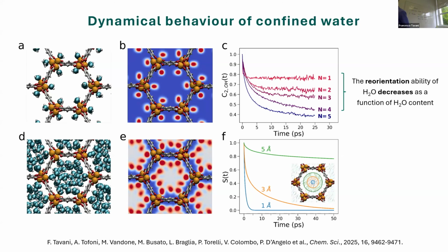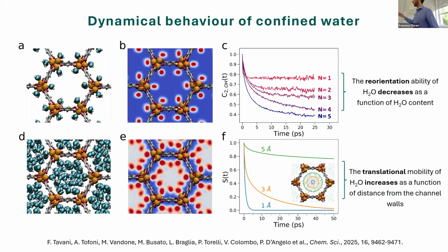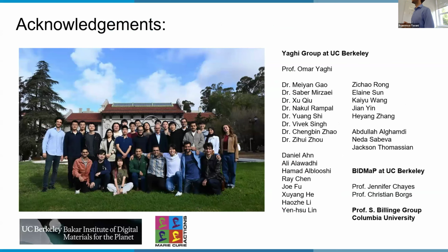If we carve sections with a cylinder shape at increasing radii, centered in the middle of the MOF at the highest water loading, and we calculate the probability of finding water molecules within these increasing volumes, we find that the probability of finding water in the middle of the cylinder is quite low. It decreases quite fast. This means that water is moving away quickly from the middle, and it moves away less quickly if we increase the radius. So basically, the translational mobility of water increases clearly as a function of distance from the channel walls. So with this, I wanted to conclude.